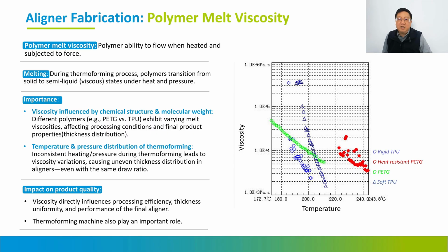So you can easily measure that using thermal diagrams, or you can use an industrial CT scanner, or use some optical scanner to measure the thickness distribution of the aligner, to make sure you have the right thickness distribution on the aligner or not. And also, I would say the thickness usage ratio is also important.